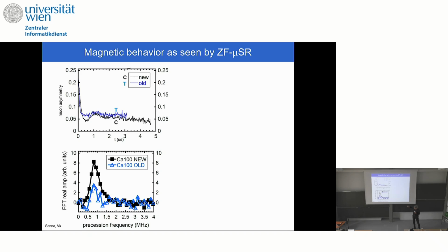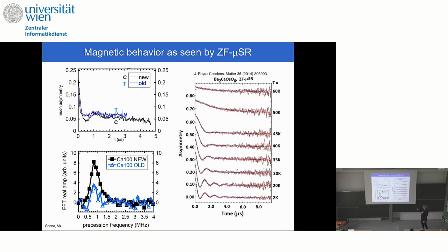Here is the Fourier transform of these two signals. You can see that the peak is at the same precession frequency, which means that the mean field probed by the muon is the same, but what changes is the coherence length of the oscillation, of the precessions. This is very similar to what was already mentioned this morning from this previous paper, at least for the one which is cubic, and they found it is cubic the same.